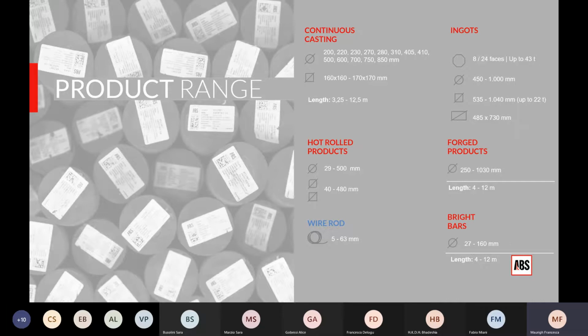We have a wide range of continuous cast blooms, most of them in round section, starting from 200 millimeter up to the biggest size, the jumbo size of 850 millimeter round. And this wide range of conti cast blooms is allowing us to offer to the customers a wide range of hot rolled products as well, starting from 29 up to 500 millimeters of diameter for round bars. Then, of course, if needed, we can either peel or turn or perform some kind of finishing to enlarge even more this range of products.